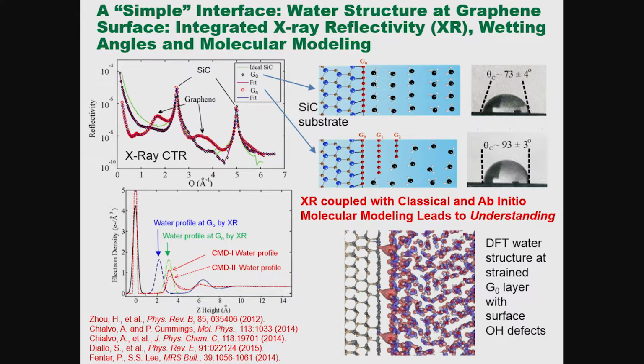The punchline is that in order to explain all of this behavior at both multi-layer graphene and monolayer graphene surfaces, we had to tweak the computational models and introduce surface defects in the form of hydroxyl defects decorating the surface. That gave us a nice match with the X-ray reflectivity. So even though we tried to make a perfect simple interface, graphene on planar SiC, it's stepped, multi-layer, and also defective. This is a pretty typical example of about as simple as you can get with an interface.